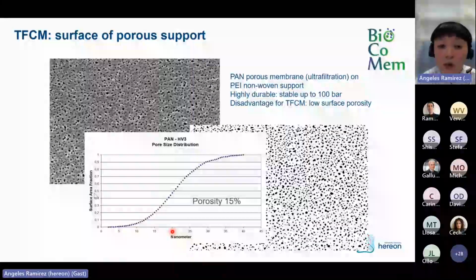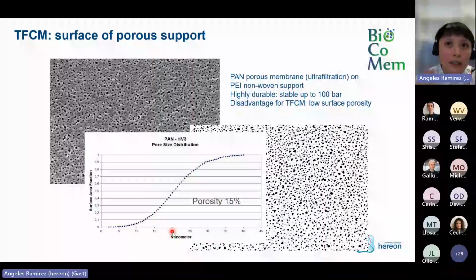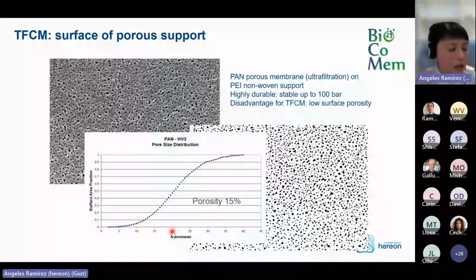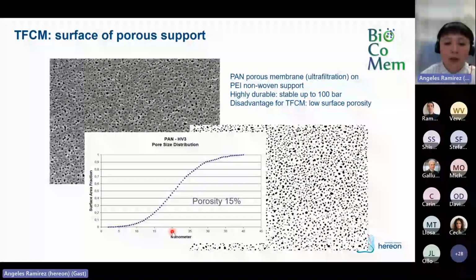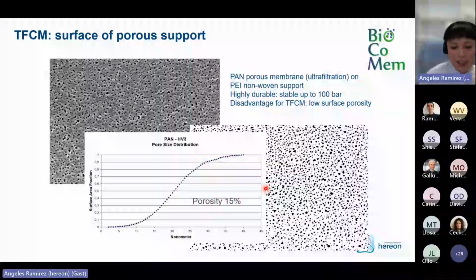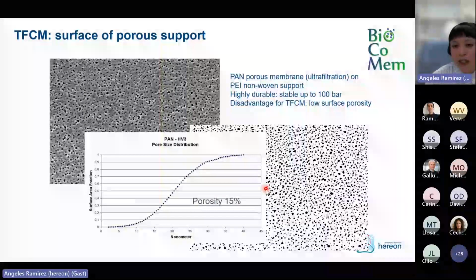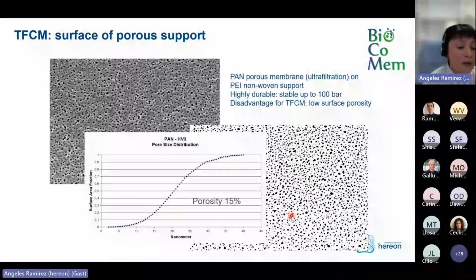That is, these pore sizes have to be smaller than the thickness of the selective layer that we are planning to deposit on top. So here we have a surface porosity for this type of membrane of around 15%. And this is, as you can see, not too high, especially considering that polyacrylonitrile is a non-gas permeating polymer.